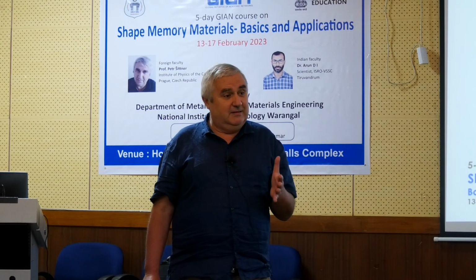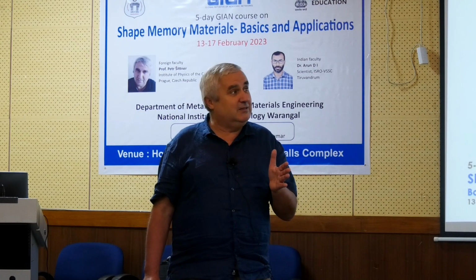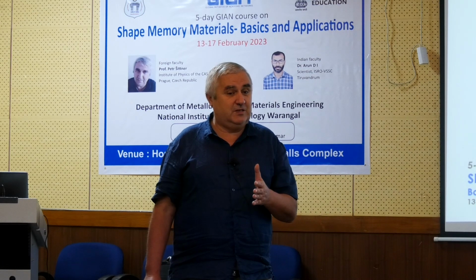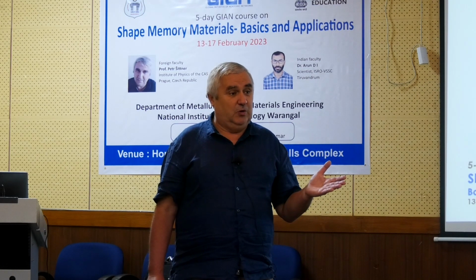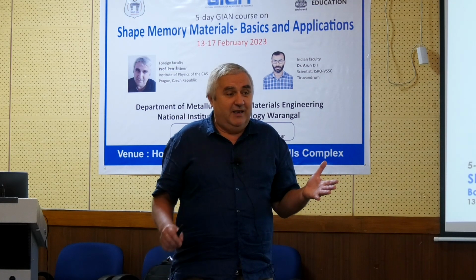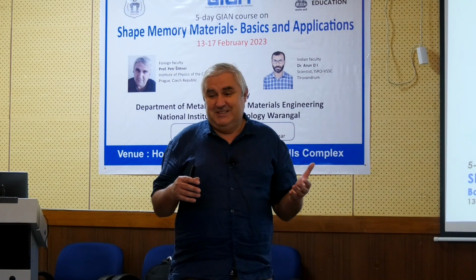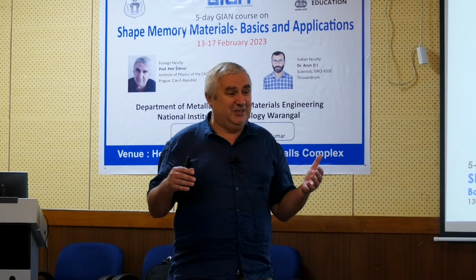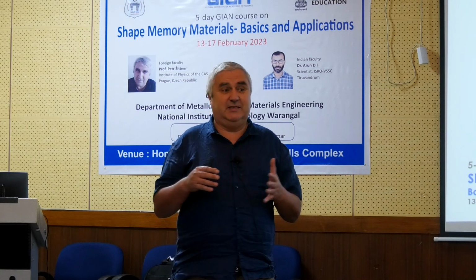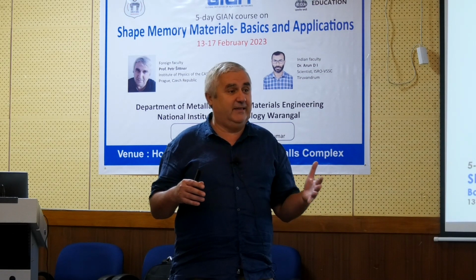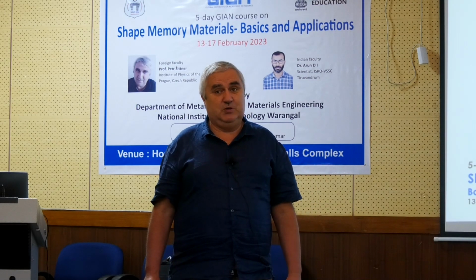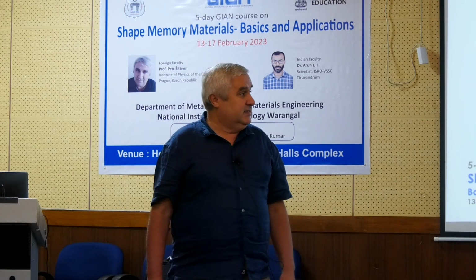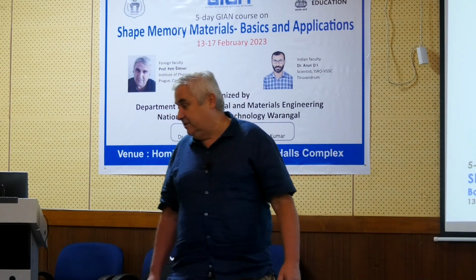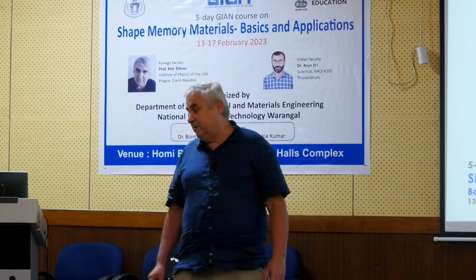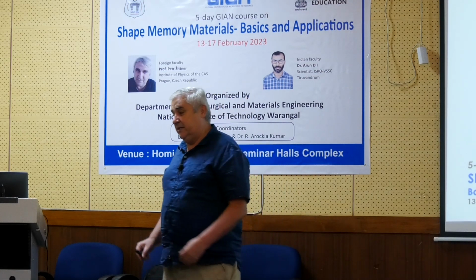in future such high entropy shape memory alloys can substitute NiTinol, because there is a problem with NiTinol. It has lots of softness which we have to fight all the time, and these high entropy alloys are inherently resistant to plastic slip. So this is a very nice development, and maybe in future NiTinol will not be that important, but so far, these days, it is.